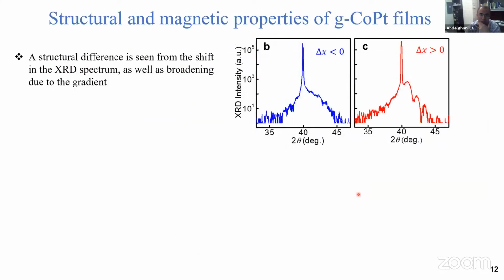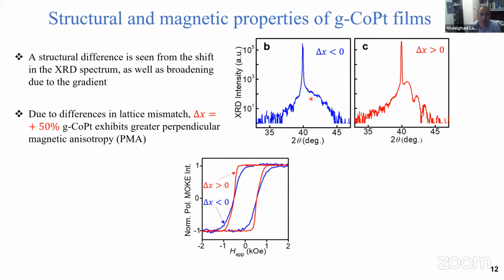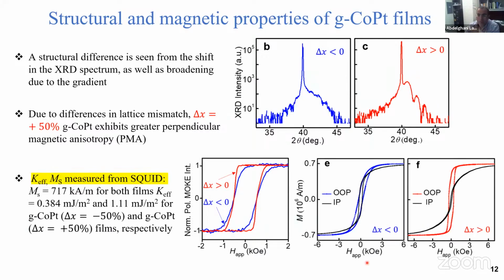Our colleagues in Singapore did characterization using XRD. You see a well-defined peak. Also, there is some broadening, which confirms you have a gradient composition in your thin films. They also measured the normal polar magneto-optical Kerr loops. And we find, in particular for positive gradient, these films have near perfect square loops, which is indicative of PMA, perpendicular magnetic anisotropy. We also did some SQUID measurements in plane and out of plane. So we can know that Ms is still the same for both films, whether positive or negative gradients. There is a slight change of anisotropy. I can explain later exactly why you have that little change in anisotropy.